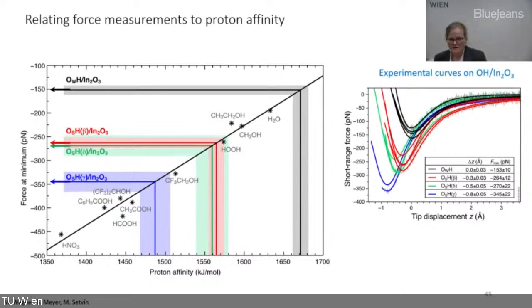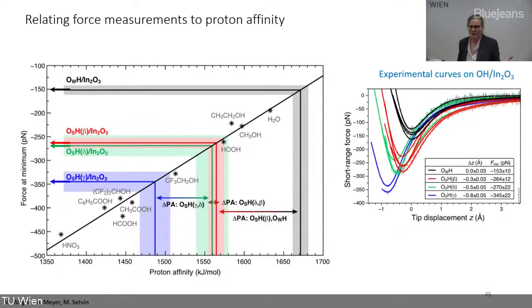This is really interesting because for the first time we can assign to one type of hydroxyl a specific single-site proton affinity. There are no calculated values to compare this to, because as DFT people will appreciate, it's not easy to calculate something involving a charged system. What we can compare to, though, is changes in proton affinities, and those agree quite well.